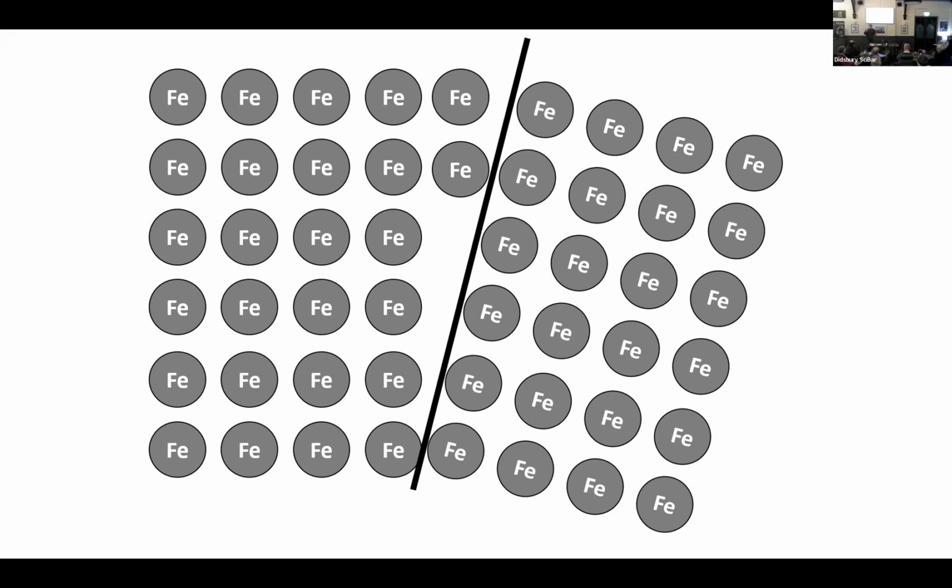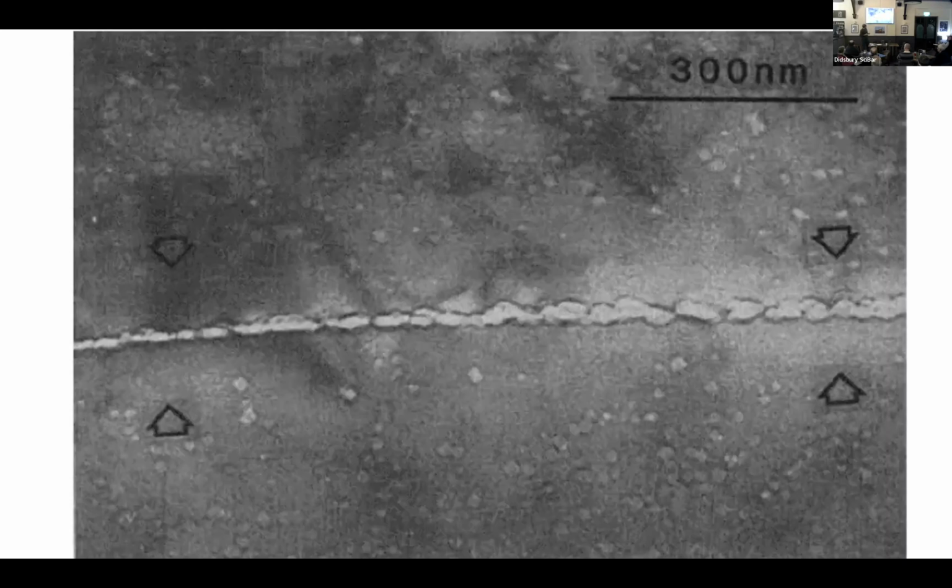So essentially you've just emitted a helium nucleus and it can pick up 2 electrons like that, not a problem. You've now got a helium atom. You've now injected gas into your material. And now you've got these regions where the gas likes to migrate to. This is one such boundary. This white line is helium inside your material. And we go back to that serrated paper.